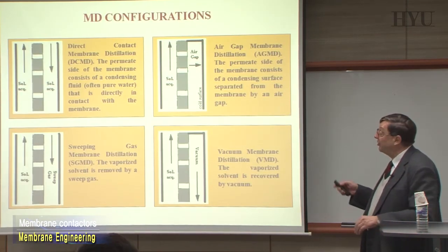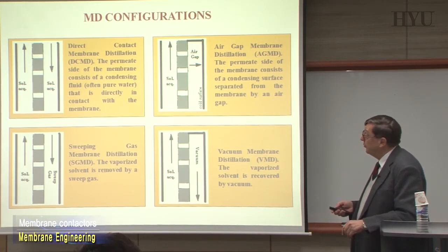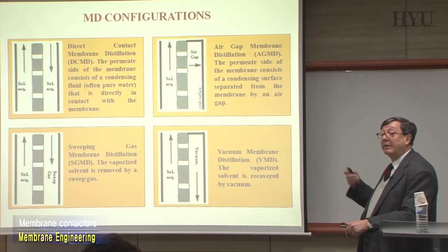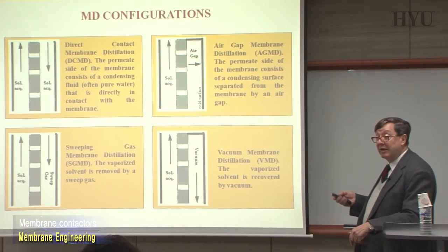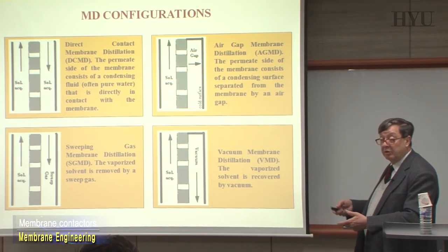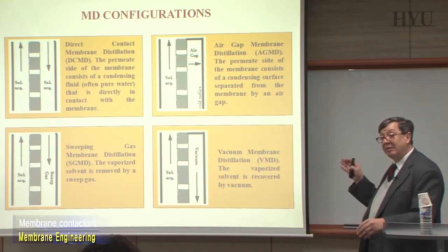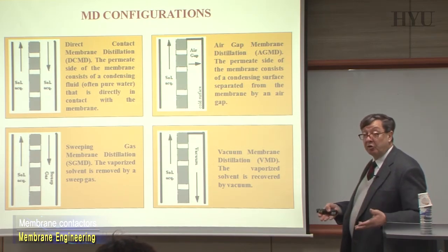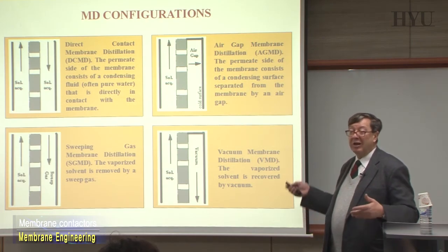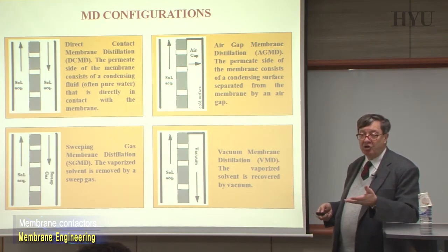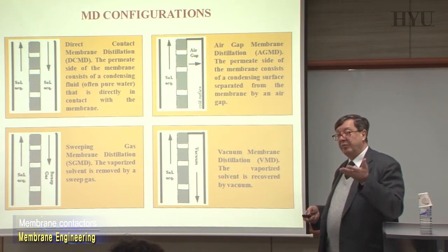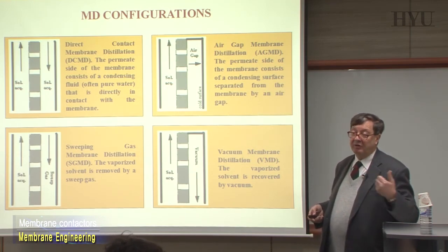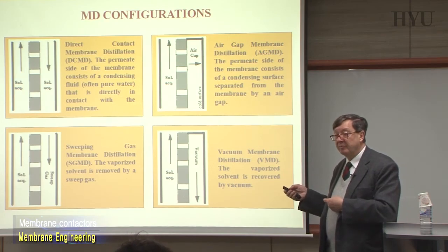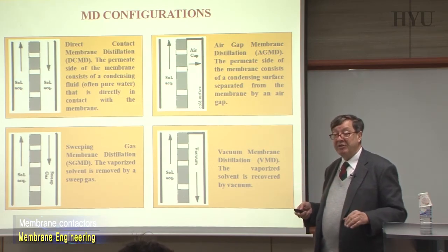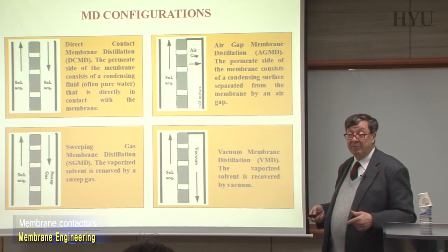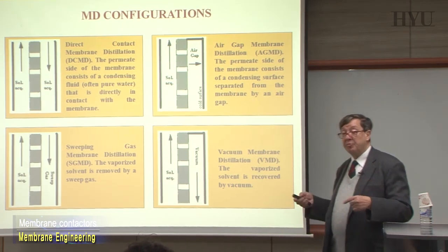As I was mentioning, you can realize this concept that we showed before in different forms. New ones will probably appear, and already now engineers and good researchers are studying how to optimize the system to overcome some of the drawbacks. For example, today we are losing about 50% of the energy that we are giving. Instead of using this energy for the evaporation on the feed side, we are warming up the polymer. So we lose about 50% of the energy in just warming up the polymer, inducing temperature polarization, nothing positive.